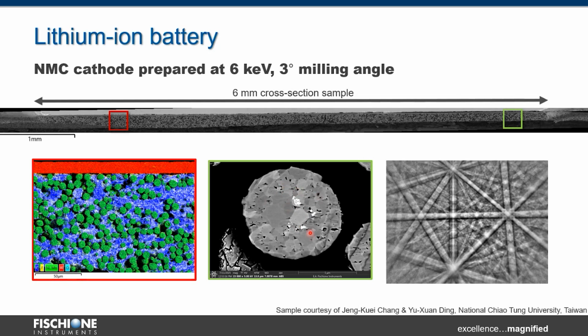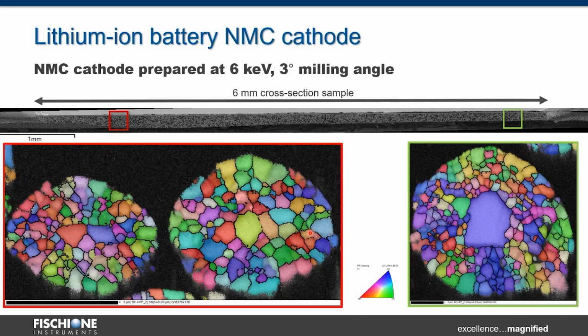And of course, for EBSD, as shown before, you get excellent pattern quality, and you can collect very nice, high quality EBSD maps, so high quality data that will help you to understand your structure and develop your application. You can get very nice statistics because you have a large area, so you can accurately calculate your grain size and overall crystallographic orientation, which is texture.